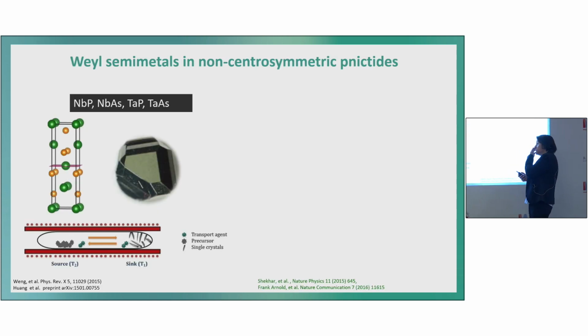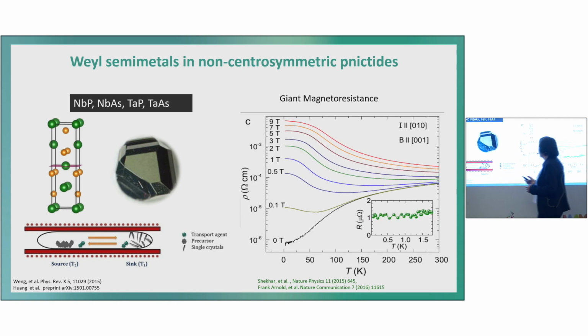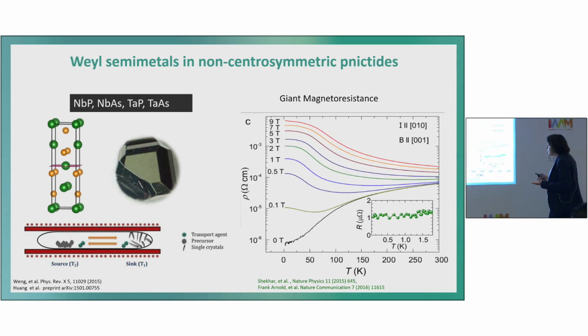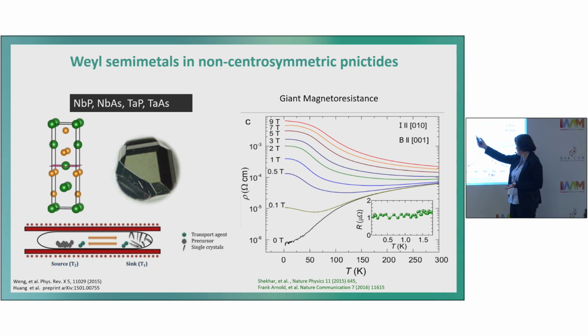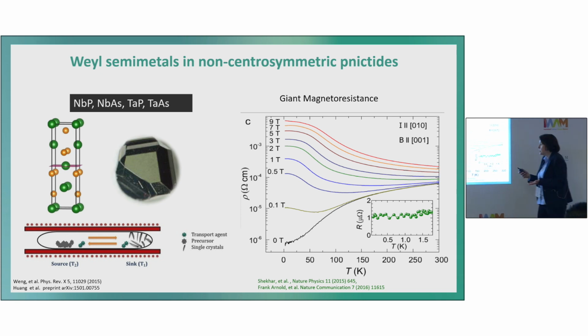So this was done by several people, but we also looked for this, and I simply use this as an introduction. This is a non-magnetic Weyl semimetal. It's a big family, niobium phosphide. It was very simple to make by chemical vapor transport. And the first thing which we saw in our samples was this giant response. Here you see the resistivity versus the temperature, a 0 Tesla measurement, and it behaves like a metal.